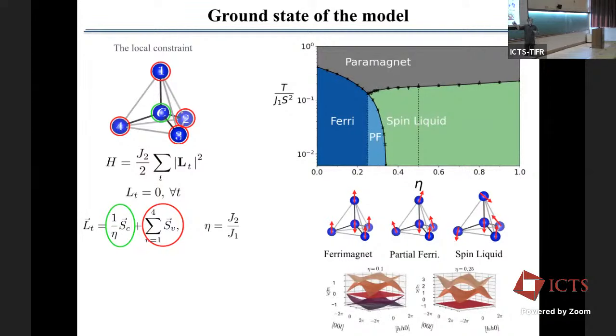You can show exactly that the flat band of this spin liquid is degenerate 4 times, with a gap to a dispersive band. And that means that 2/3 of the bands are flat and correspond to the spin liquid. So from the point of view of the spin liquid, this is a very, very, very disordered spin liquid. For example, Pyrochlore, it's 2 flat bands over 4. Kagome, it's 1 flat band over 3, which means that the fraction of flat bands with respect to the total for this one is much bigger than both the Kagome classical spin liquid and the Pyrochlore classical spin liquid. So this is a very disordered phase.